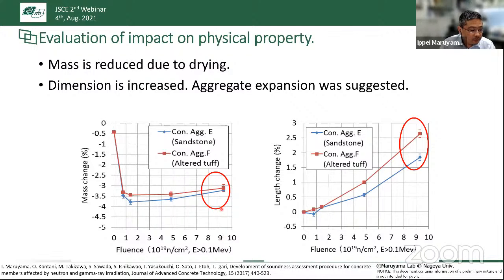On the contrary, we see the expansion. The magnitude is quite large, as you see. In the case of the concrete with the coarse aggregate with a high amount of alpha quartz, it expanded to 2.5%. And in the case of the concrete which contains the sandstone, with about 50% content of alpha quartz, it shows less expansion, but still the amount of the expansion is very large. It is almost 2% after a neutron fluence of 9 times 10 to the 19 neutrons per square centimeter.